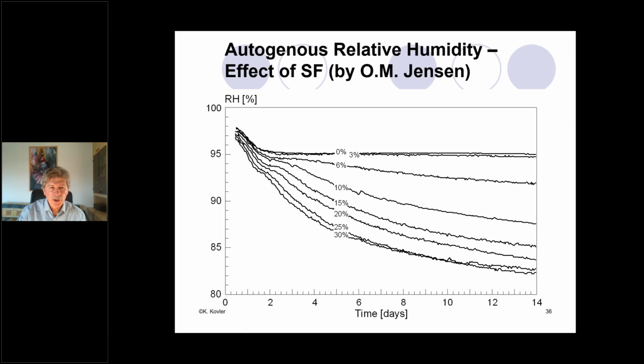This chemical shrinkage is accompanied by autogenous shrinkage and self-desiccation. Self-desiccation is a direct result of chemical shrinkage. This diagram was taken from one of the works of Professor Jensen from Denmark. You can see that the addition of silica fume increases the self-desiccation, and the relative humidity in the system is dropping.